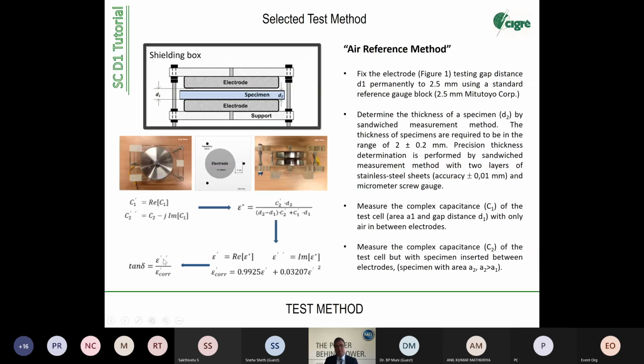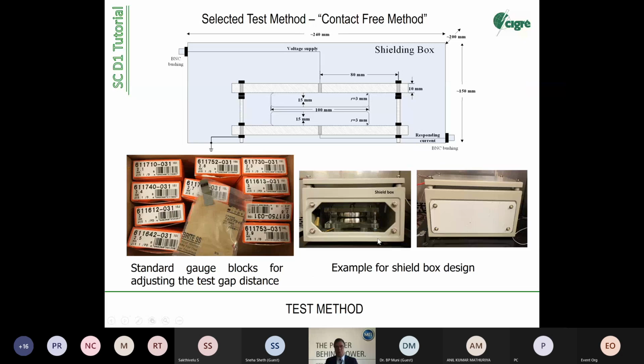This is how our selected method was defined. So this is a technical drawing, more or less, of how we defined the test procedure for the round robin test. We also defined how to connect this with the BNC bushing, and we put everything in the shielding box, made a standardized connection to the voltage application, grounding, defining everything, which was in the lessons learned very good, because if you start to make your own equipment or to work with undefined equipment, that's a big source of error. We already learned that from former working groups, that we clearly have to define test equipment and arrangement.